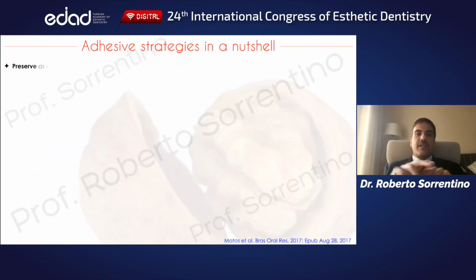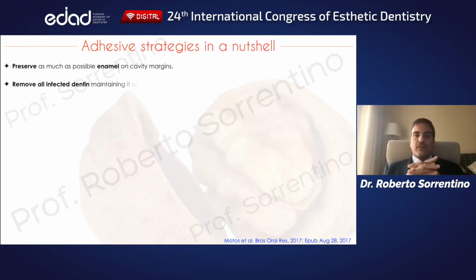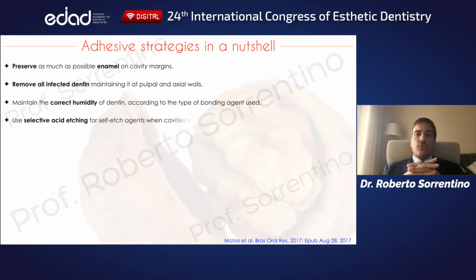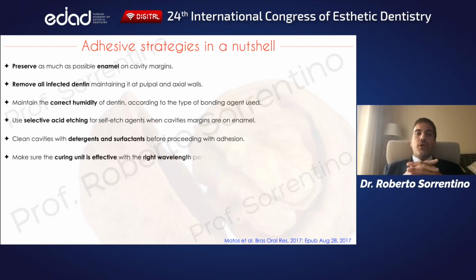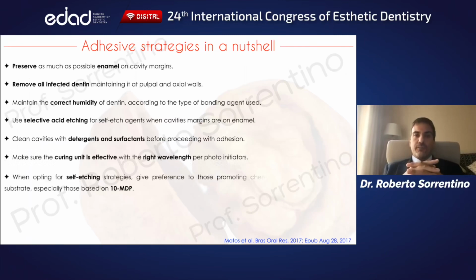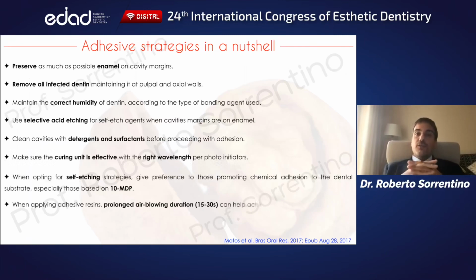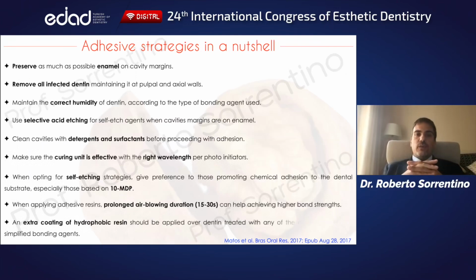Preserve as much enamel as possible, mainly on the restorative margins. Carefully remove all contaminated tissues, particularly the infected dentin. Keep the proper moisture content according to the chosen bonding technique. Use selective enamel etching with simplified or universal cements on the margins. Clean up thoroughly dental surfaces by means of surfactants and dedicated cleaning solutions.